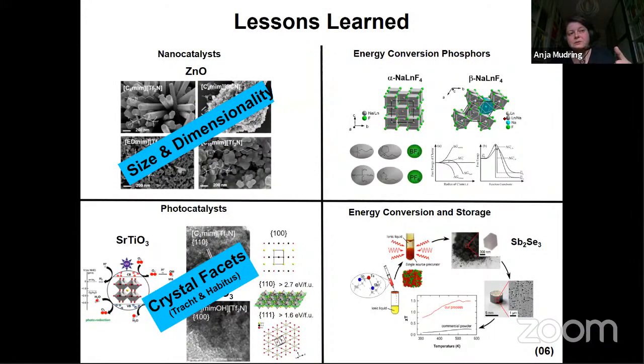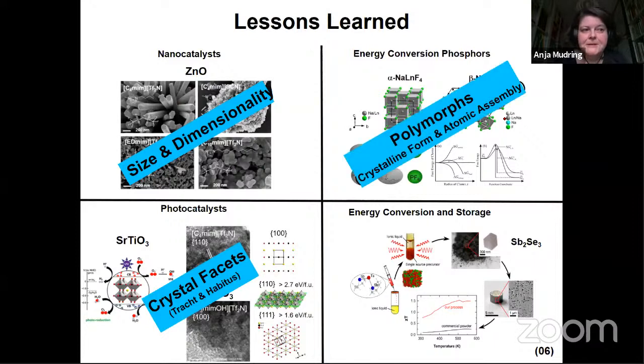So when you produce the material, you want to direct the reaction outcome towards the one polymorph that is beneficial for your application. And again, you can tune that through playing around with the surface terms when you generate the nanoparticle. And that's again determined by what is attaching to the surface. And that determines the activation energy for crystallization, and in the end guides you towards one or the other polymorph.